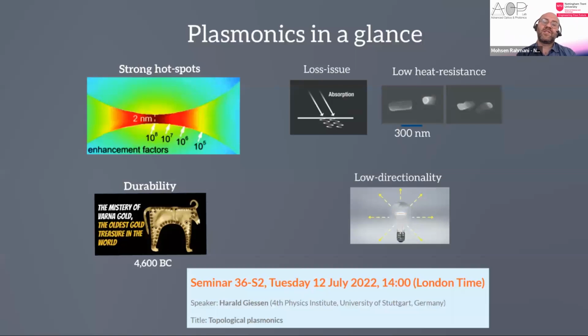Plasmonic nanostructures suffer from ohmic losses. They absorb light a lot, and they have very low heat resistance, as you see over here, in particular for the nonlinear regime. When you are putting some high power laser, when you want to excite the nonlinear interaction, you easily can burn. As you see here, it was a dimer, but it's already burned.